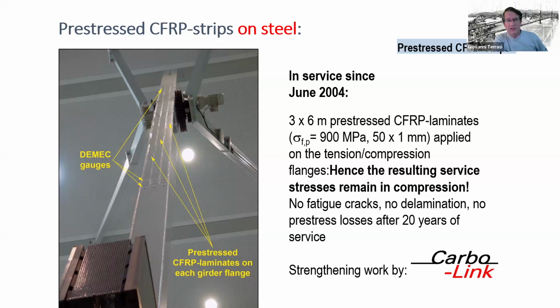So we used 3 six-meter long pre-stressed CFRP laminates, 50 times 1 millimeter in cross section. I would say that was a quite special Carbodur S510. We defined it in the short meeting we had before, pre-stressed to 900 megapascal to induce 45 kilonewton of pre-stress load per sheet, bonded with an elastomer-modified adhesive, an adhesive which is in use in the aircraft industry. It's used by Airbus, a 3M product, to have a very ductile kind of adhesive on our steel.